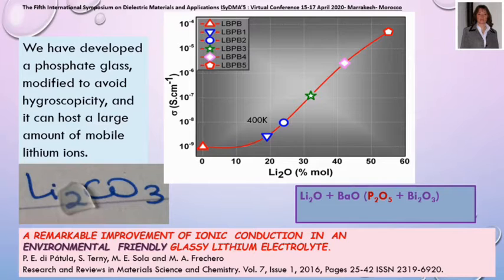One of the greatest glass matrices obtained in our lab was a phosphate glass modified with bismuth and barium oxides. This glass is particularly non hygroscopic, and it is able to contain a large amount of lithium oxides, lithium cations. As you can see in this plot, a high conductivity at moderate temperature is reached, with a low activation energy also, and is a very good glassy material, as you can see in the picture on the left side.